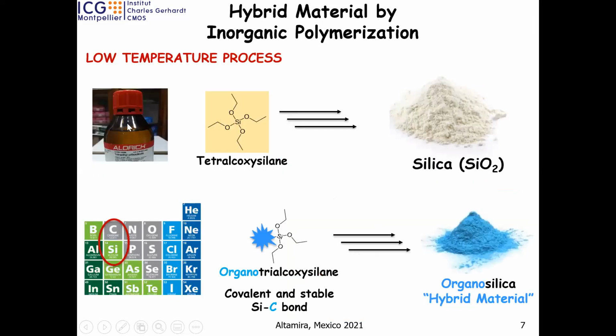Here, just a small cartoon. We start from tetra-alkoxysilane, and we can get silica, classical silica, SiO2. The advantage of silicon is that it's in the same column as carbon. They have a similar chemistry. I mean by this, if you take a silicon-carbon bond, it's very stable. Acid treatment, basic treatment, it's stable. You can't cleave this silicon-carbon bond. However, a carbon-aluminum bond is not so stable, and a carbon-titanium bond is not stable, because we are not in the same column.